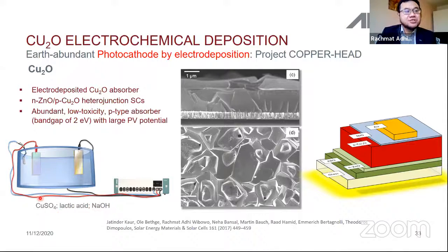So from the solution of copper sulfate, lactic acid as a buffer and complexing agent, because you need to stabilize the copper. If you don't use lactic acid, the copper will precipitate directly. And we use very high pH using NaOH, sodium hydroxide, at pH 12, which is a bit alkaline.